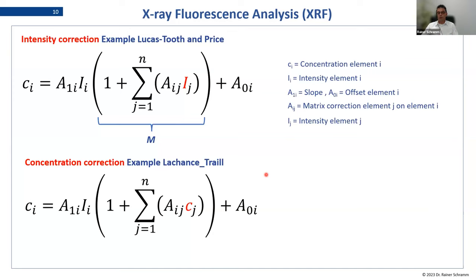Now you see there is a bit of a strange situation, because in the beginning, we don't know the concentration. So what we do is that in the first estimation, the concentration is calculated without matrix correction for every element in our sample. And then when we know the concentrations, we can do our first matrix corrections. And then we get new concentrations. And this way, in an iteration, step by step, we will approach the final concentrations, which are then fully matrix corrected.